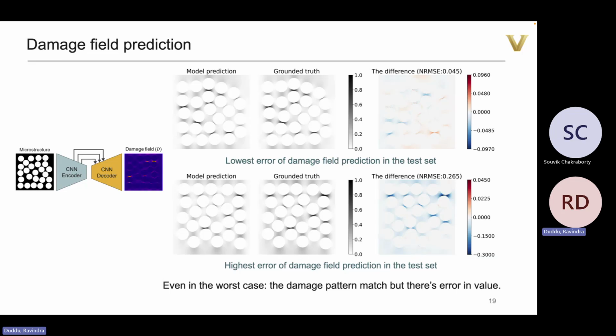What's the stiffness mismatch? Like, what is the ratio of the stiffness of the fiber and the matrix? We took the properties of an epoxy matrix and a carbon fiber. So it's quite high, like maybe 2 to 3 orders of magnitude.